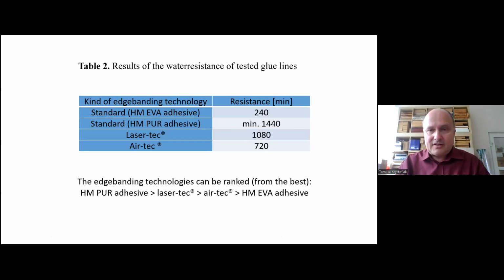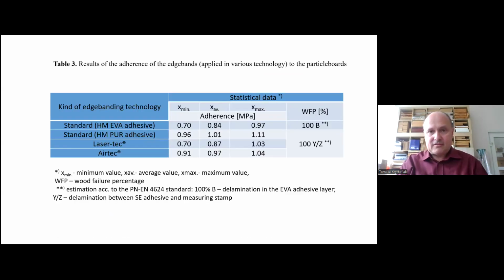And water resistance in minutes of tested materials. And you can see that laser-tec, air-tec, using these systems give us results similar to polyurethanes and significantly higher results than standard adhesive. Adhesion strength, laser-tec, air-tec, mixed delamination, and it is delamination between the adhesive used for gluing stamps.